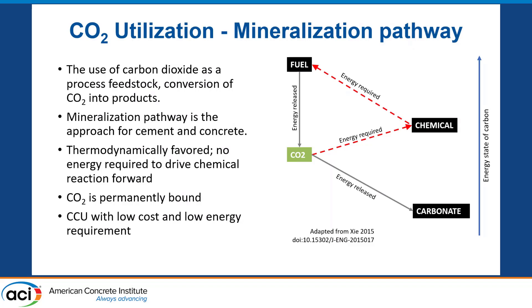Specifically, what does utilization mean within concrete, and how does the CO2 end up coming into the concrete? It's where you're using the CO2 as a feedstock in the production of something — in this case concrete, but it could be a chemical or something else. We're advantageous in the concrete sphere because when you use CO2, it's mineralized, and that's actually converting the CO2 to a lower energy state, which means, as opposed to converting it into a fuel, you don't have to add energy to break the carbon bonds and perform something else.